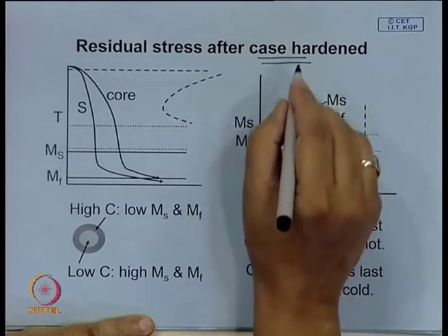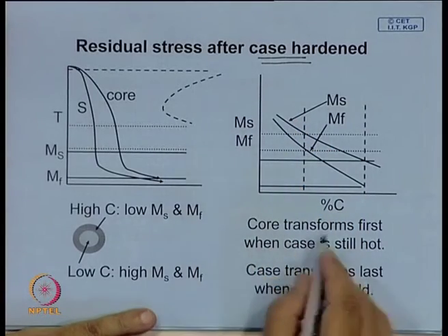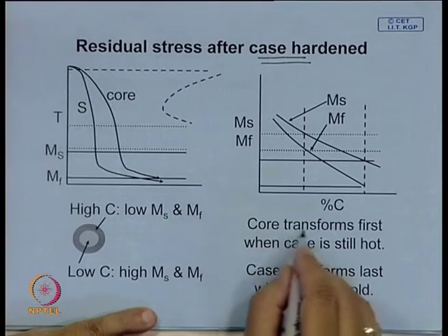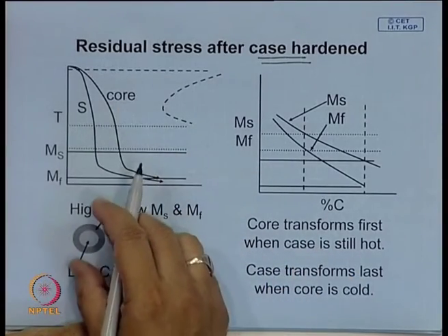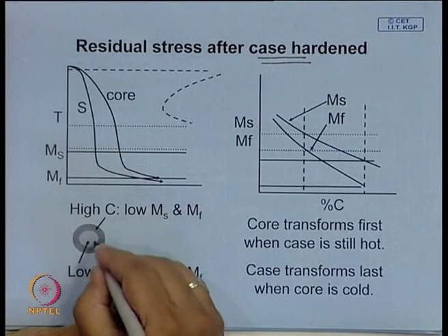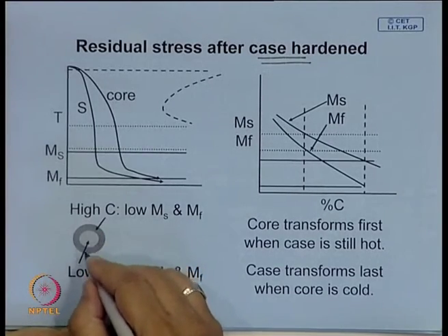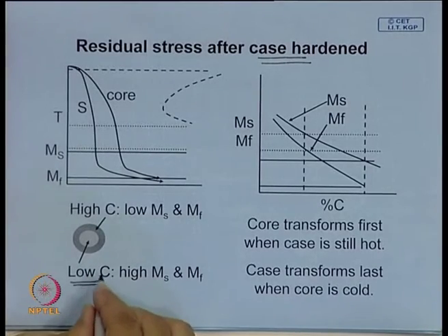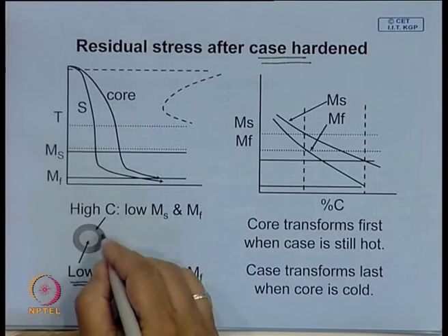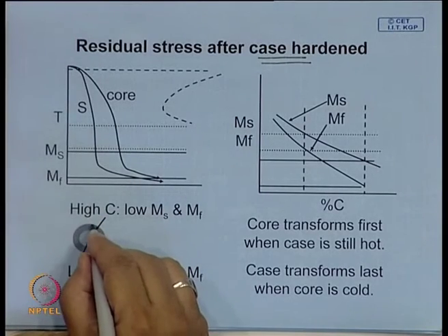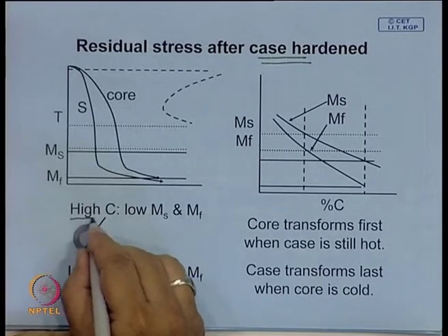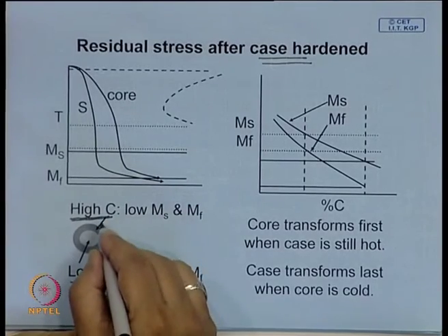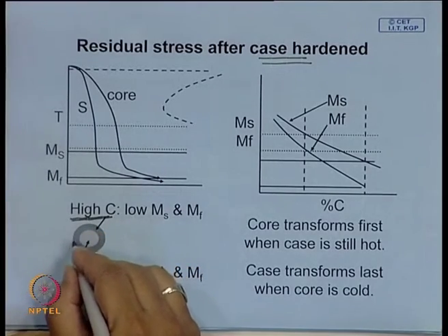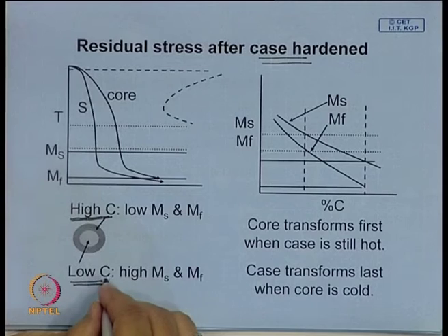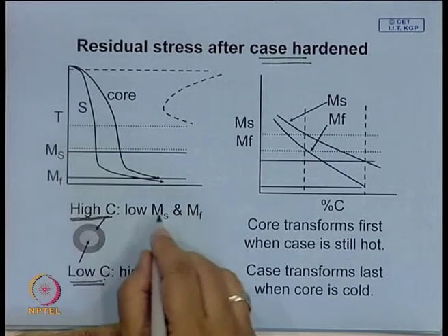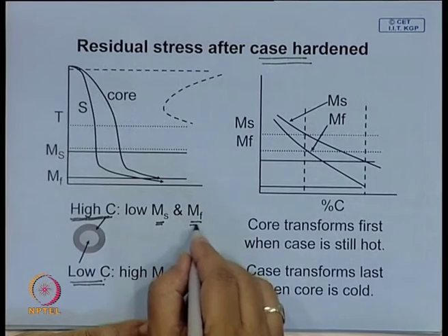I am projecting this here because I just realized there has been some mistake which I will explain. When you have a large section, you want the core to be tough. So one would prefer a low carbon steel, and since it cannot be hardened through and through, the attempt is made to enrich the carbon content of the surface by different carburizing processes like pack carburizing or gas carburizing. You increase the carbon content of the case, the core remains low carbon, and when you make this modification, the MS and MF temperatures decrease.